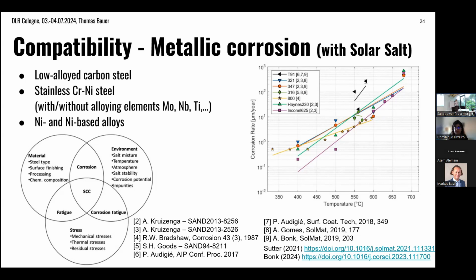And then if we have very severe applications with high heat fluxes and so on at receivers, at molten salt heaters, where we have even higher temperature, then sometimes also nickel-based alloys are used in limited applications. You can see here the corrosion, of course, increases with temperature very strongly. That's a logarithmic scale. But the data scatter quite a lot. And that's also because the environment, the salt, plays a strong role, how you treat the salt. Is this an experiment in a very small crucible? Is it in a big crucible? How decomposed was the salt? This will all have an impact on the corrosion rate you observe. So the attacking medium, the salt, is very important to look at, how it was treated and so on, if you want to determine the corrosion rate.